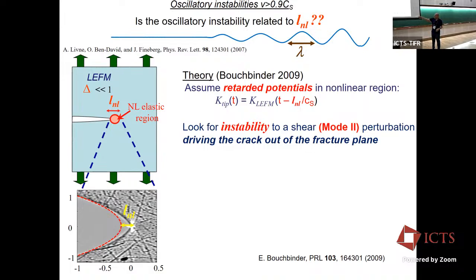But this reacts according to the characteristics within this nonlinear zone, which is really, really stretched, okay? So energy is being fed, but there's a phase lag because it's a different material. So in a sense, there's some kind of material mismatch at the boundary. And so this material reacts to the energy flowing into it, but not instantaneously. Okay, so that's what this is saying.